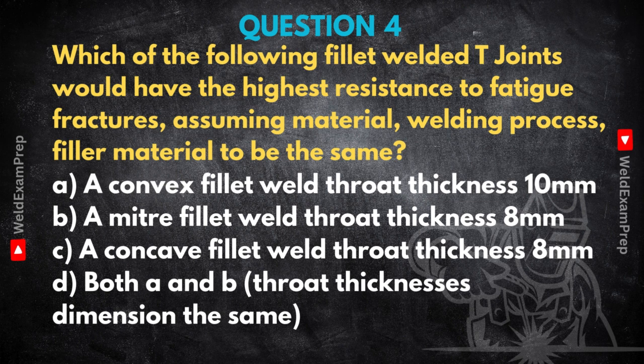Exactly. And the answer, perhaps counterintuitively for some, is C. A concave fillet weld, throat thickness 8 millimeter. The concave one, even though it's smaller than option A. Yes. And the reason boils down to stress concentrations. Fatigue failures from repeated loading and unloading are incredibly sensitive to sharp corners or changes in geometry. They almost always start at these high stress points.